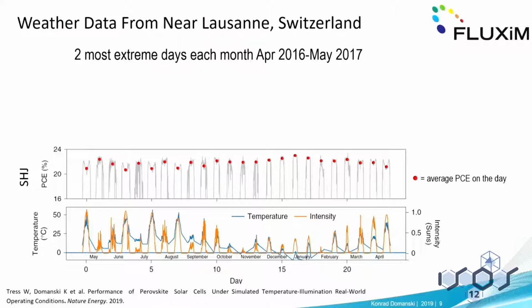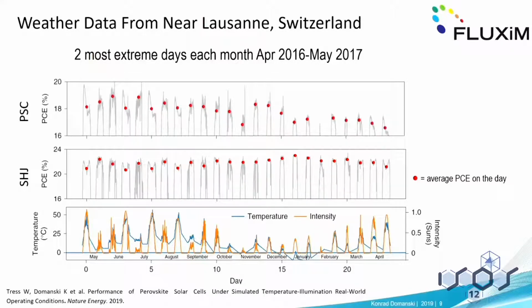And here you see the average efficiency of the devices on a given day, and we see that silicon efficiency is best in the morning and in the evening, because during the middle of the day, the temperature kicks in and we lose voltage. For perovskite, the story is really different. We see they behave best in the morning and don't really recover towards the evening. And this is because of reversible degradations. As the samples get illuminated, they start losing efficiency. We just saw several examples of that. And we also see that there is a monotonic trend towards decrease in efficiency, so an early warning about the permanent degradation.